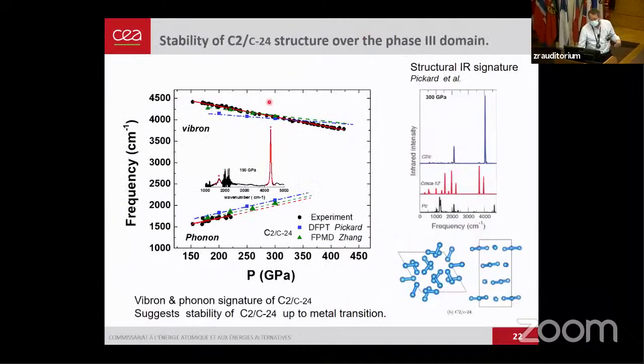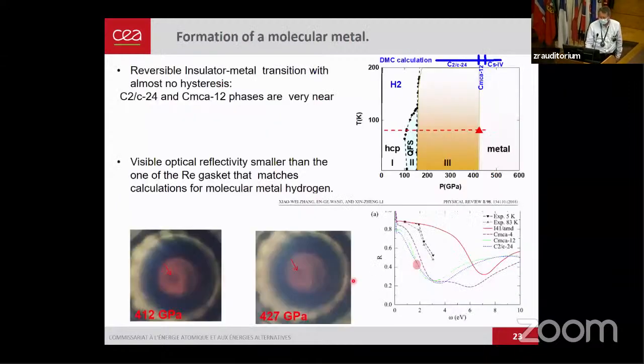We have a vibron, so we can measure the vibron and the phonon. We have two modes, vibron and phonon, which has been calculated as a signature of the phase, which is a monoclinic phase. It is like a hexagonal plane with a molecular line in the plane. This has been predicted by ab initio calculations, and we are observing this kind of infrared signature of this phase. So we believe this phase is stable until the metallization. And since we have a reversible transition, we believe we have formation of a molecular metal.